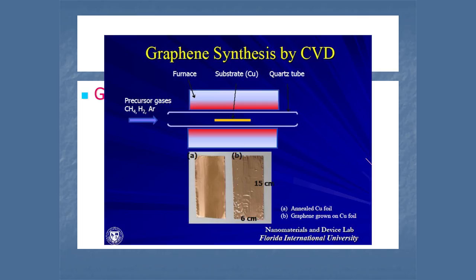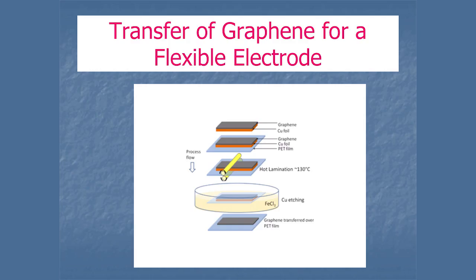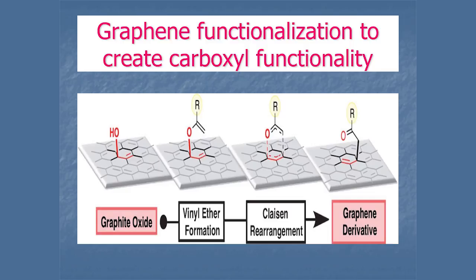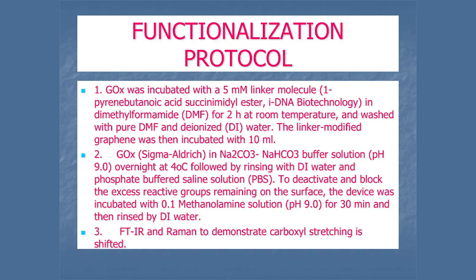Now, graphene synthesis is straightforward. That is by CVD, chemical vapor deposition. I will not go into it. Transfer the graphene for a flexible electrode. Then the functionalization to create carboxyl functionality, the same thing we did with the carbon nanotubes. Now, the functionalization protocol: GOX was incubated with a 5 mM linker molecule, a simple organic molecule, in dimethylformamide for 2 hours at room temperature and washed with pure DMF and deionized water.